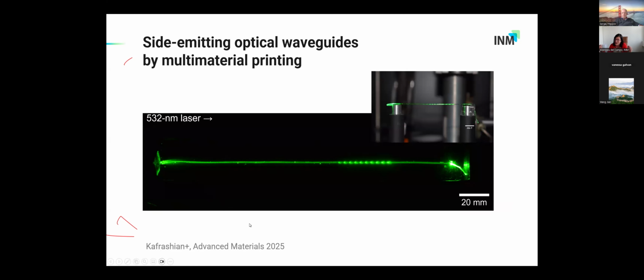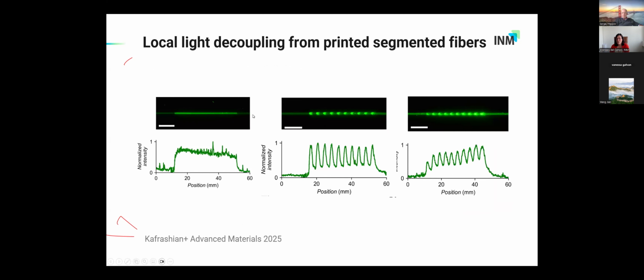So the waveguides are physical objects. You can couple light. You can use them. The beauty of the fact that we can print segmented fibers, or that we have this multi-material printing process, is that with that we can control the length and also the profile of the outcoupled light. We want to outcouple where the bacteria are later on. And depending on the switching profile, we can either outcouple over a long segment or outcouple in short segments as we want. Here you see the intensity of the outcoupled light along the fiber.